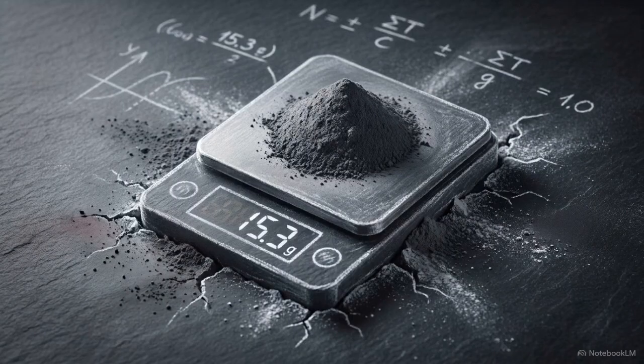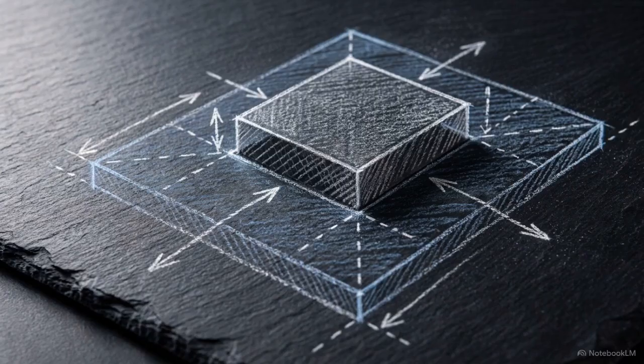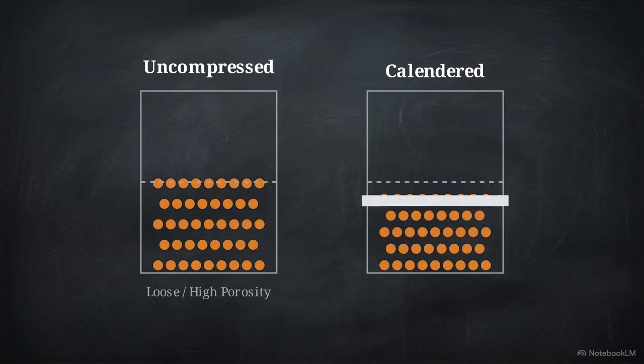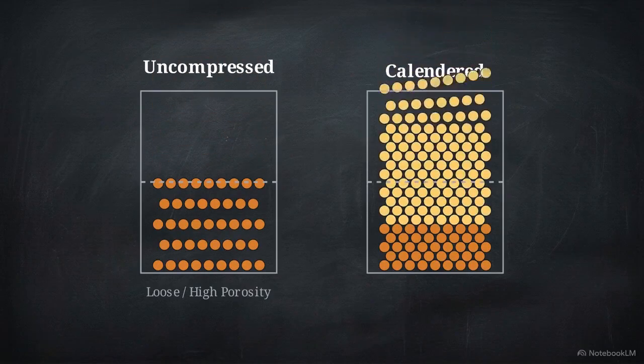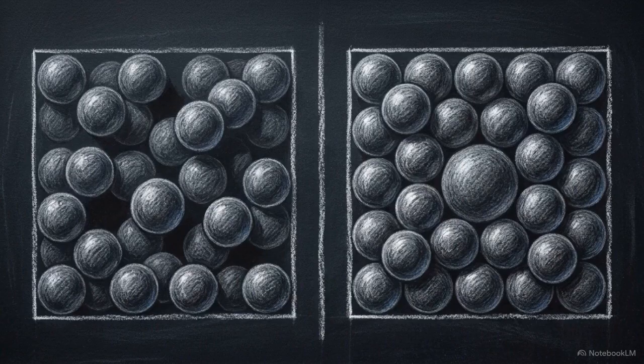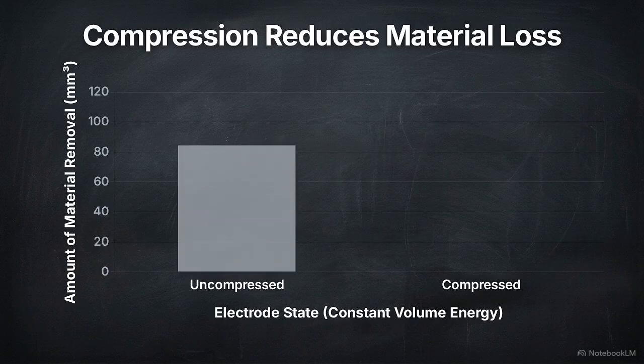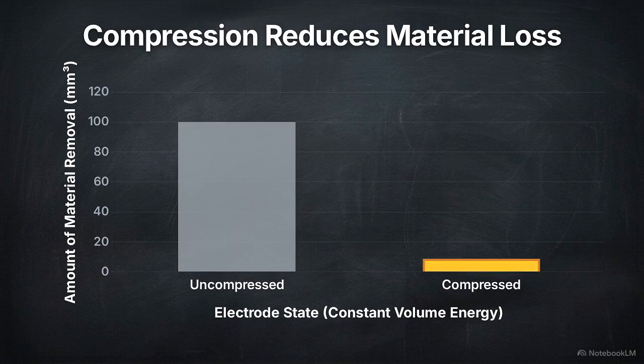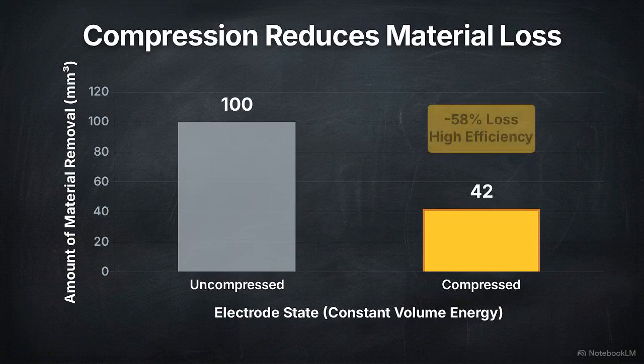But specific capacity only measures charge relative to mass. For real-world device performance, the decisive metric is areal capacity, the total charge storage available per physical unit of area. Because the calendering process packs the active material tightly together, compressed electrodes begin with a higher initial mass loading. You are fitting more chemically active material into the exact same spatial footprint. We also have to account for the amount of material removal during manufacturing. As this chart shows, compressed electrodes suffer far less active material loss when subjected to identical laser energies.